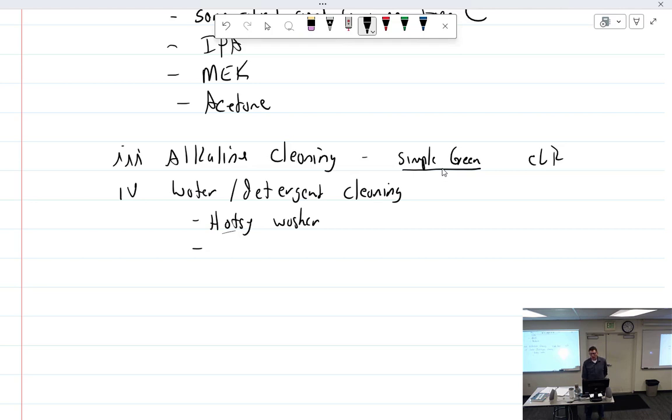Okay. So what I wanted to mention about Simple Green is that it was a big go-to for a lot of aircraft owners because it is a good degreaser. But, and I want to say it was Beechcraft, came out with a service bulletin that said stop using that. It's a heavy alkali cleaner that gets between the plates of the aircraft and causes internal corrosion between the plates. And I knew that, and I hadn't thought much about it. Of course, I'll use the Purple Power.